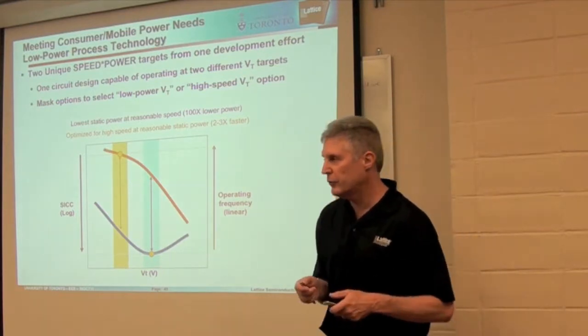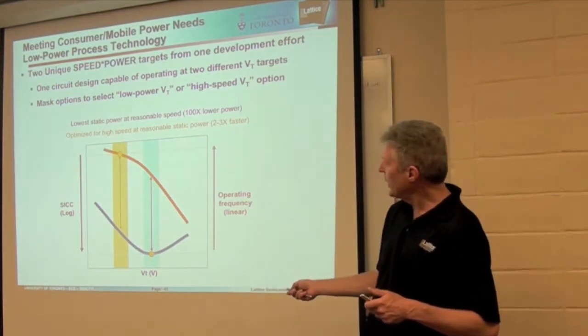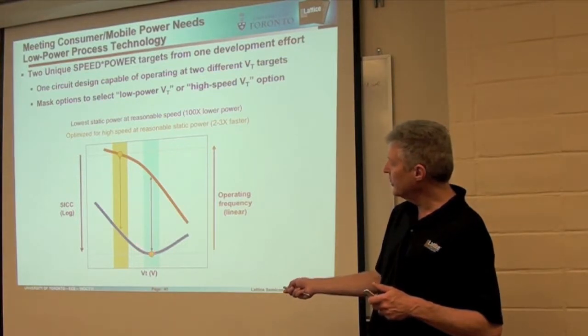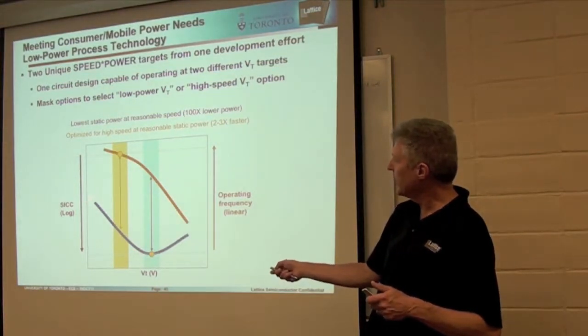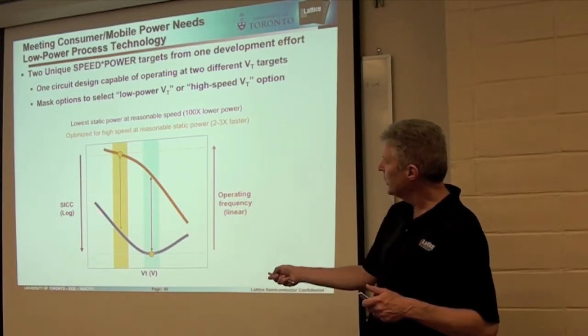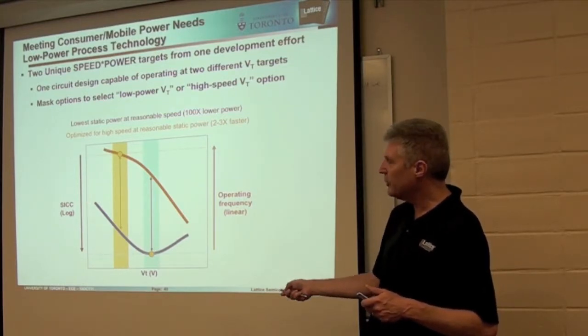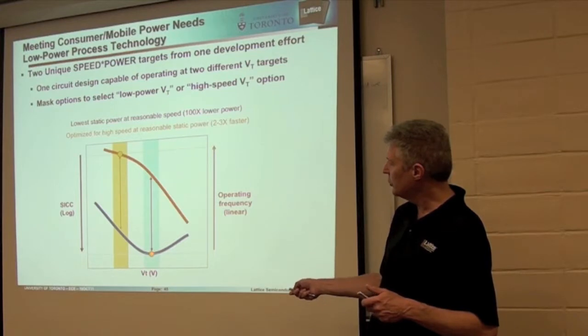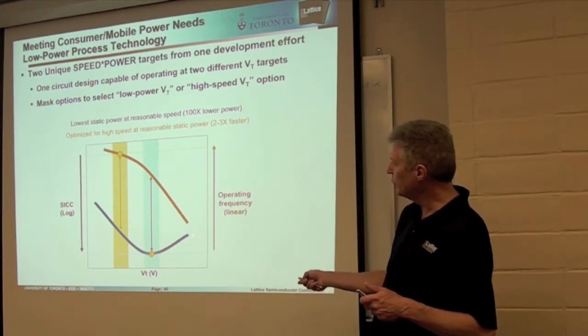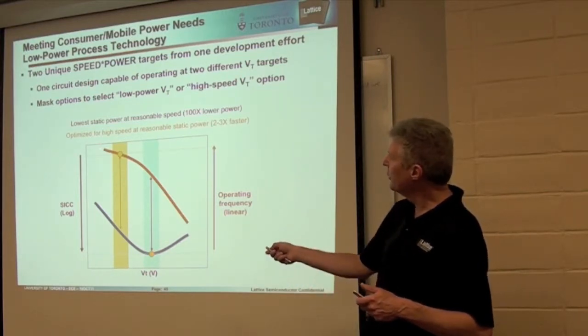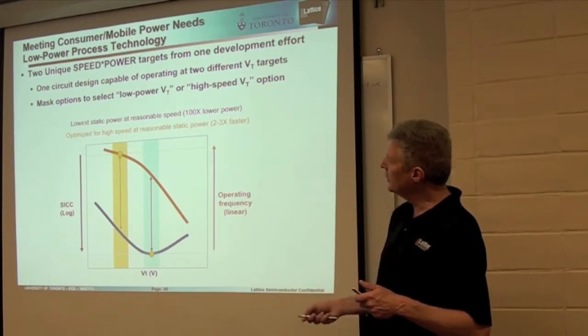That's what we did with the X02 family. So we have one threshold voltage target that is the absolute lowest static power. And what I've got illustrated here, by the way, this purple curve is essentially static power consumption. And as you can see, as a function of threshold voltage, there's an optimal point after which it starts to increase again. The orange curve up here is the